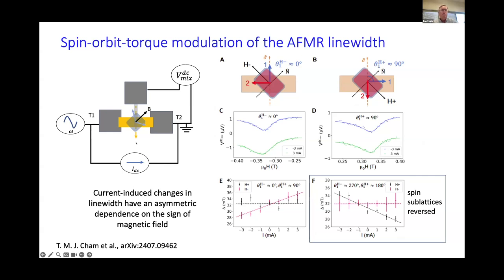What we've done is apply a magnetic field sort of oriented along the hard axis, but with the crystal oriented so that it's 45 degrees away from the current in the channel. With that magnetic field, we can tune the spin sublattices either parallel or perpendicular to the spin generated by the spin orbit torque and see what effects are produced by current, whether we change the line width or not.